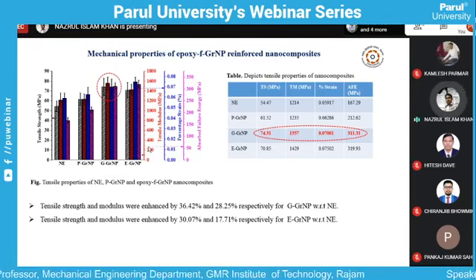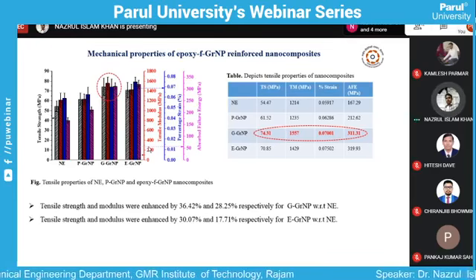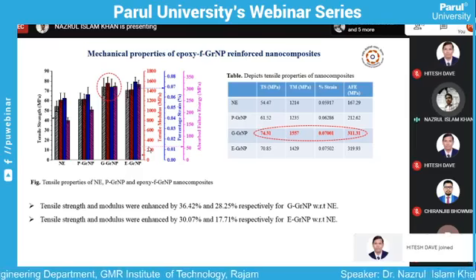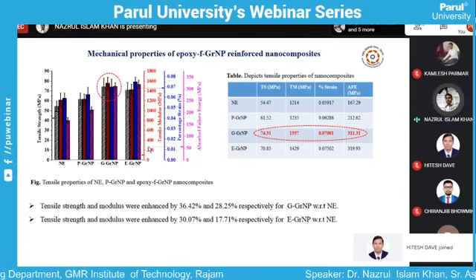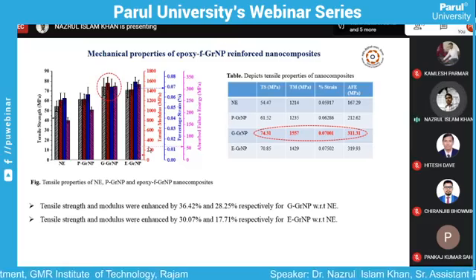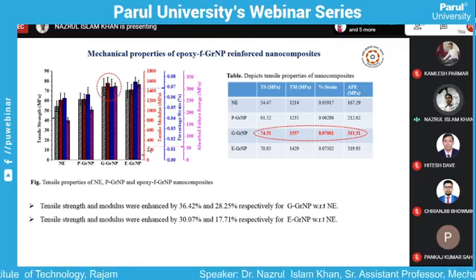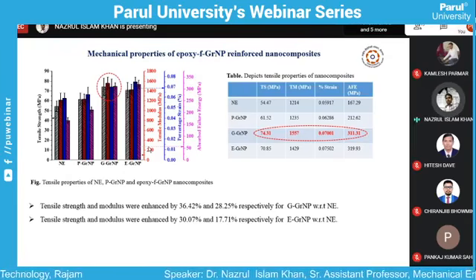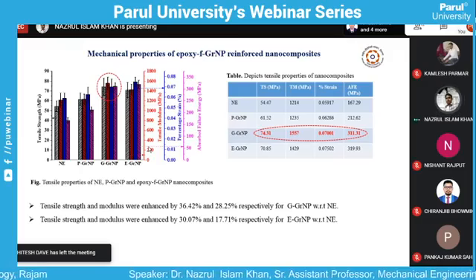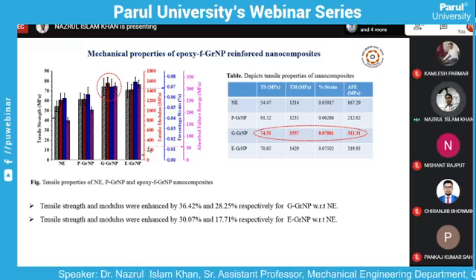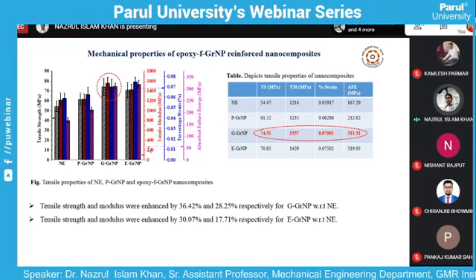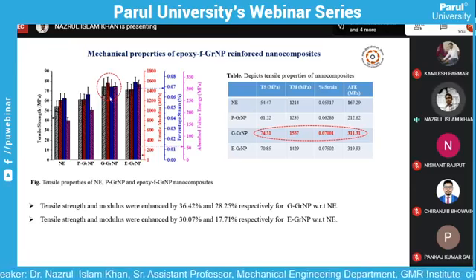This is because the epoxy ring present on the surface of this nanofiller will form a covalent bond with the amine group, which is generally present in any polymer matrix. Anyone working in this field will know these things. So this amine and epoxy will interact and take more load, if any, from the filler and matrix. If it has good covalent bonding, whenever you apply load, that load will be transferred from matrix to filler, and it will absorb more energy before any fracture takes place. It will divert the crack in random directions, and you get more energy out of the composite.